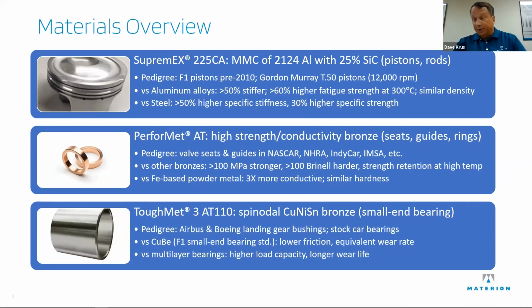the materials are our Supremex 225CA, and the 225 stands for 2000 series aluminum with 25% silicon carbide. Those of you who, 20 years ago, know metal matrix composites with silicon carbide, they were big hunks of silicon carbide. They were whiskers and things. These are very fine 3 micron diameter particles that our proprietary process distributes evenly throughout the material. This material was used before they regged out of Formula One. It was used as Formula One pistons. And its first road car use is the hypercar, the Gordon Murray T50, where Cosworth is putting the Supremex 225CA in there.